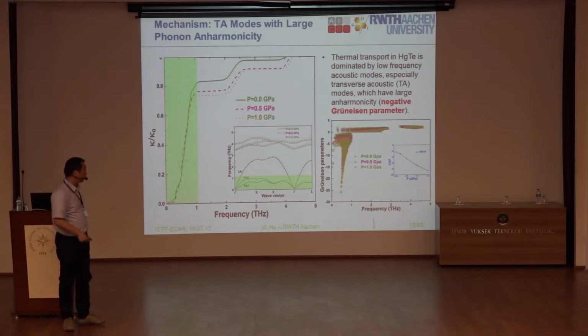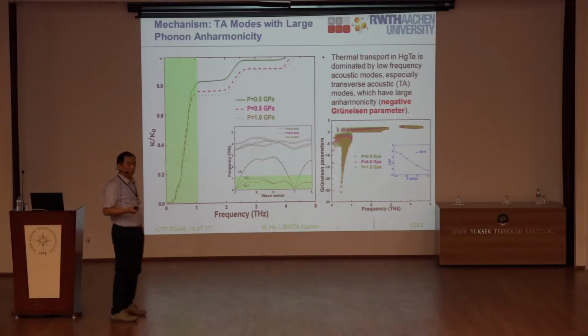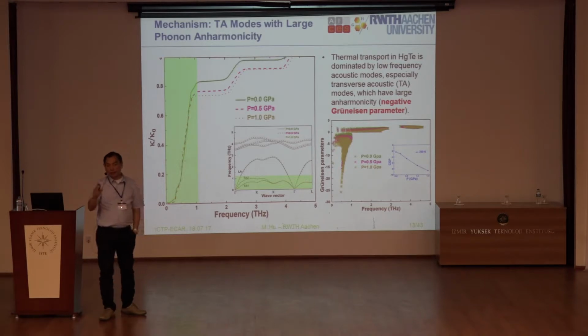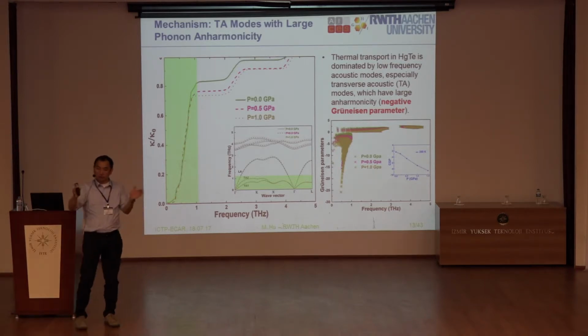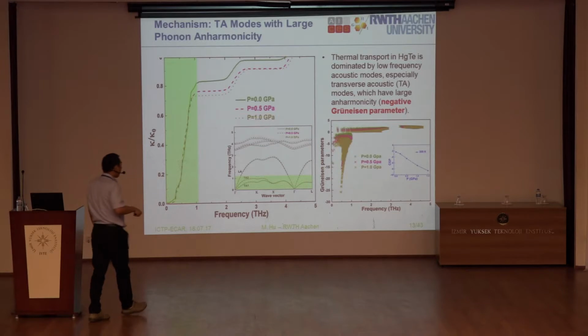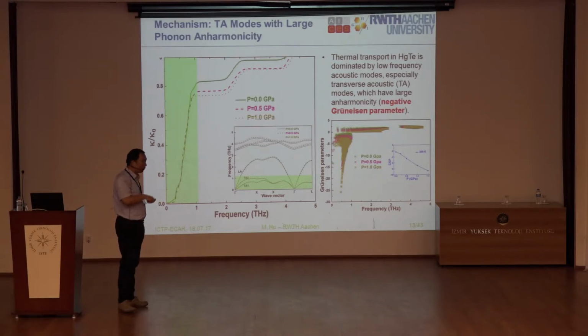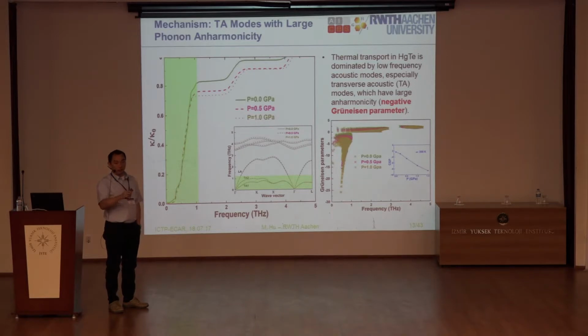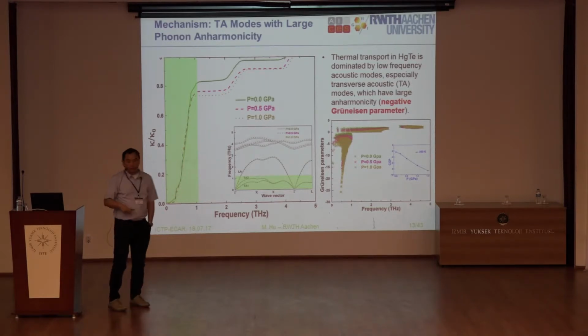If the Grüneisen parameter is very negative or dominated by negative values, the whole material will have negative thermal expansion. Of course, we do find some materials with negative thermal expansion over a certain temperature period. In mercury telluride, negative thermal expansion has also been found in experiments at low temperature, around 50 to 100 K. So here we also find that the negative thermal expansion is contributed by the TA modes.